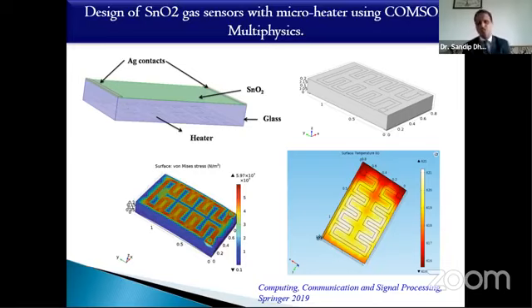To measure the resistance of the sample, we have here two contacts, or we can also have 4 contacts. But here, to make it simple, we have taken 2 contacts. And then we have studied its microheater properties. The sensing properties are still undergoing, but in microheater properties, we found very promising results. If I apply 2 volt, the temperature of the entire surface is quite uniform, and it goes up to 350 degrees Celsius or 621 Kelvin.